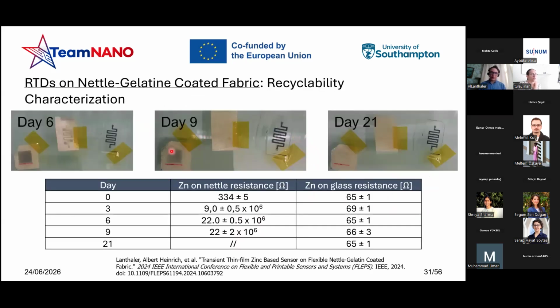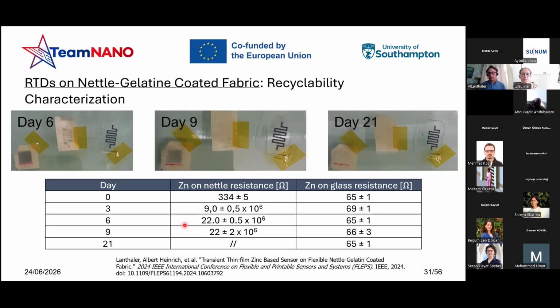To find an answer to this question, we developed this test. We fabricated the same device on a nettle-based fabric, the same as before, and, in the same fabrication process, the same device but on a glass slide, as you can see here. And we also use as a control the same nettle-based fabric with a square, in order to have a reference in terms of resistance. So after 6 and most importantly 9 days, the device was completely gone with a very high resistance in the megohms range.